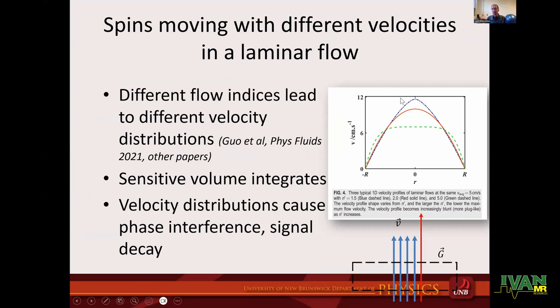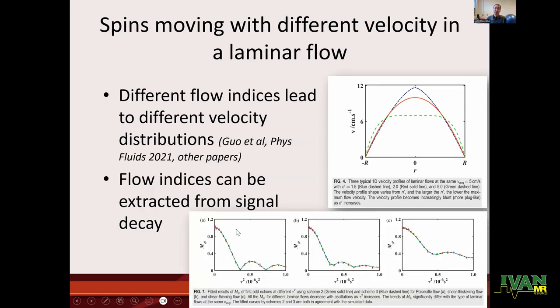Imagine a pipe with a flow in it. Typically you have a Poiseuille flow when you have a Newtonian fluid, so you have this parabolic shape shown here as a red line. When your sensitive spot is large enough to cover the whole cross-section of the pipe, the sensitive spot is your integrator. All those different parcels with different velocities are added together, and you get some signal dependence on the velocity profile. For non-Newtonian fluids, you can have shear thinning or shear thickening fluids. You have different profiles correspondingly, and that results in different signal behavior.